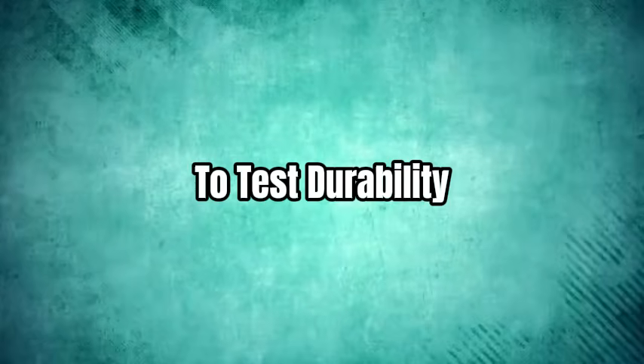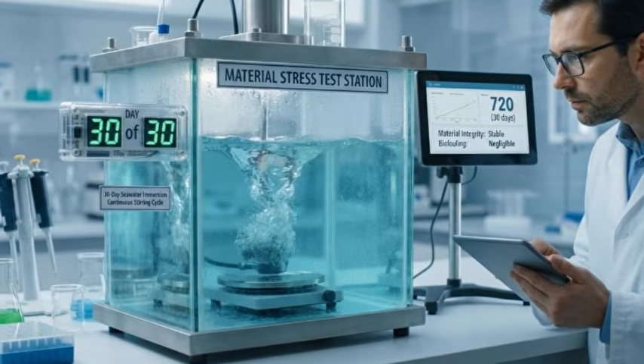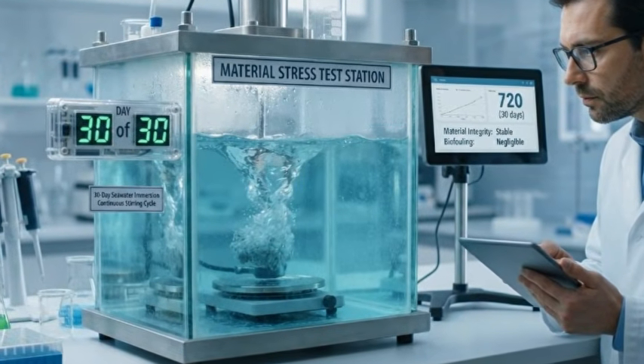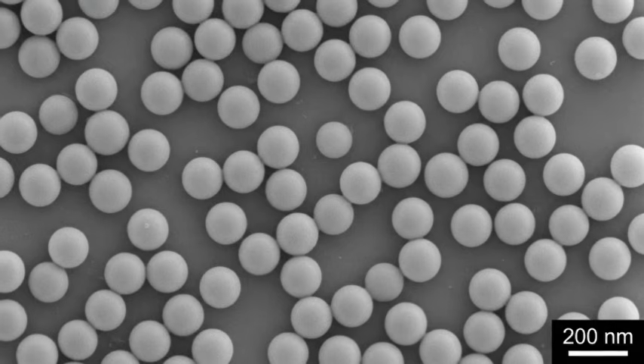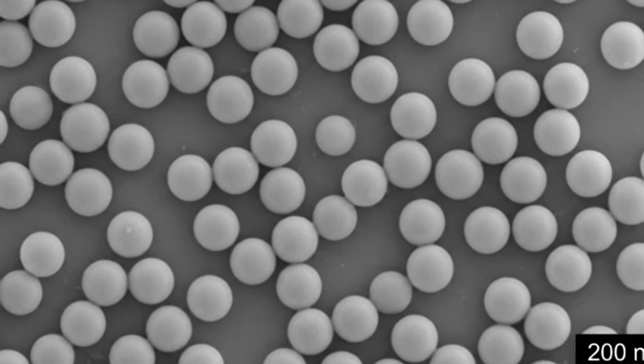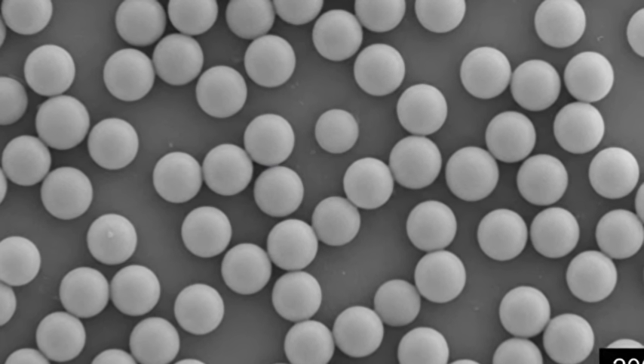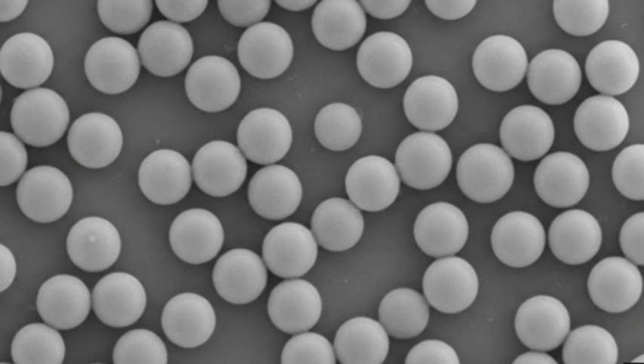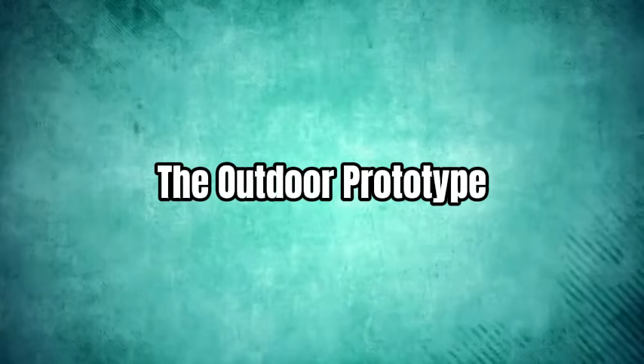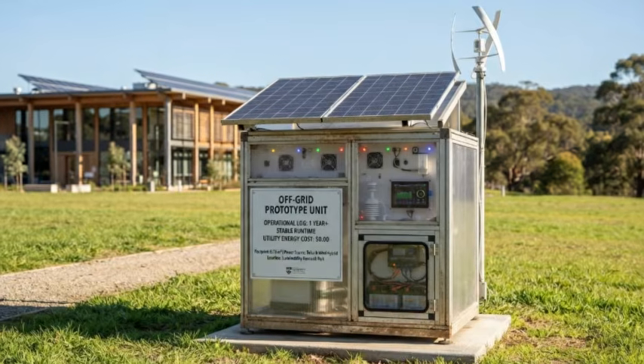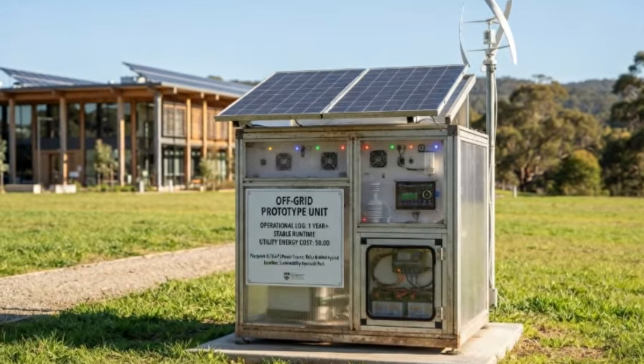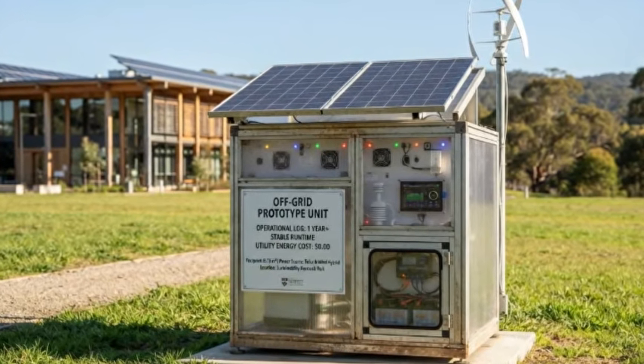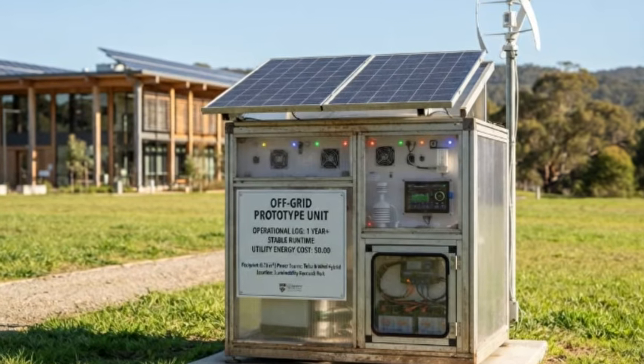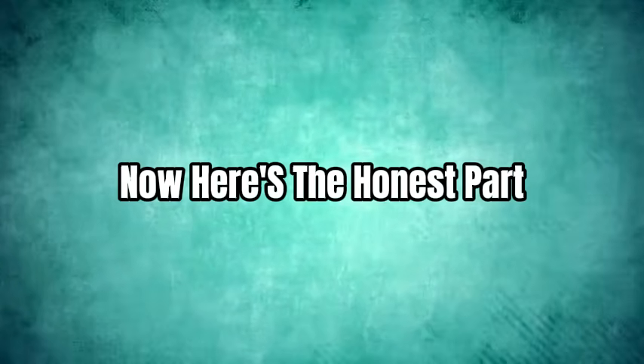To test durability, researchers submerged the material in seawater and stirred it continuously for 30 days. And microscopic analysis afterward found 0 detached particles and no sign of light-driven chemical breakdown. The outdoor prototype, built at 0.75 square meters, has now logged over a year of stable operation with 0 utility energy costs. Now here's the honest part, because this is where a lot of coverage gets carried away.